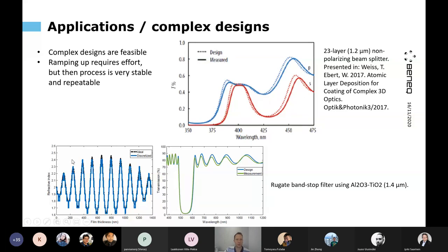In the lower example here, if you look at this graph, we are looking at the refractive index as a function of the film thickness. So this is a 1.4 micron thick film stack. And unlike usually, where you have a certain thickness of low index material and then another film of another thickness of high index material, then again certain thickness of low index, high index, that's how you make the stack normally. But in this so-called rugate design,